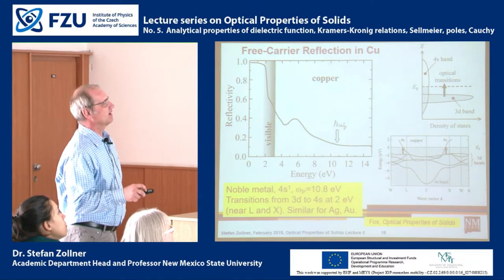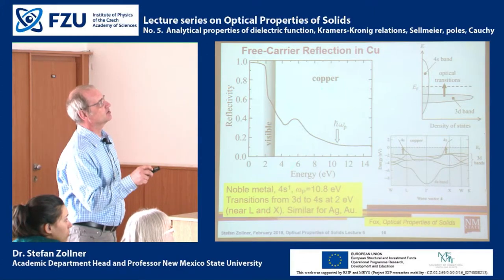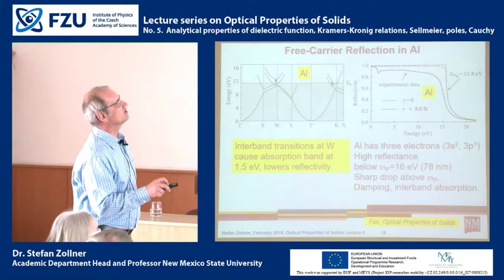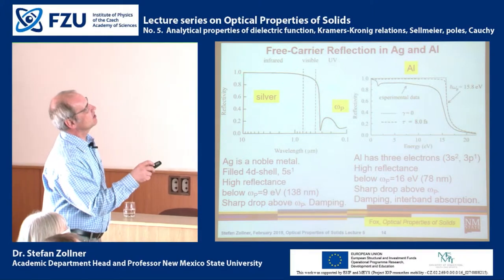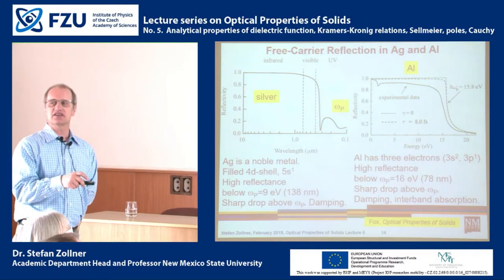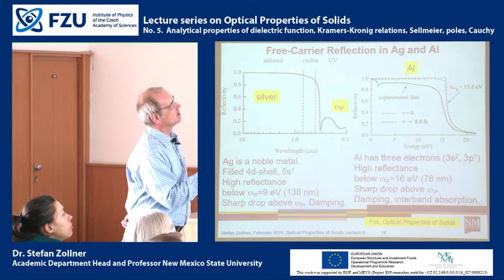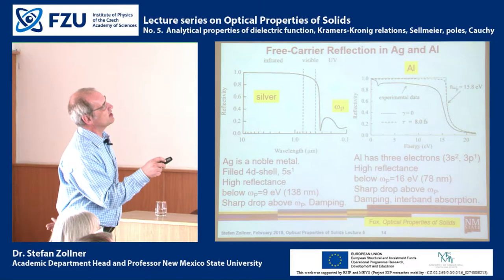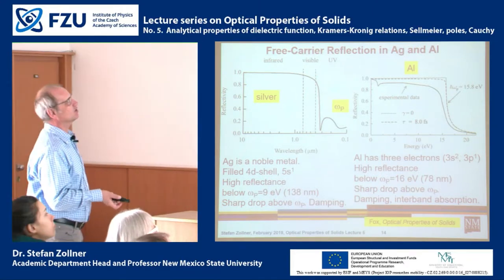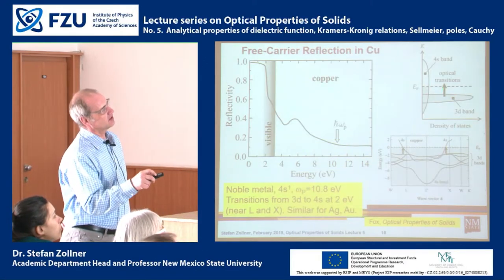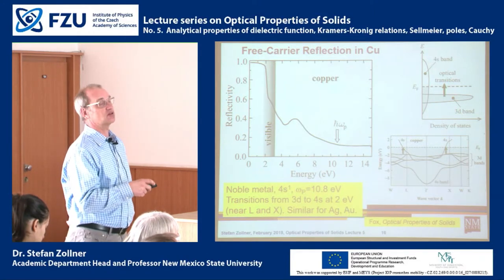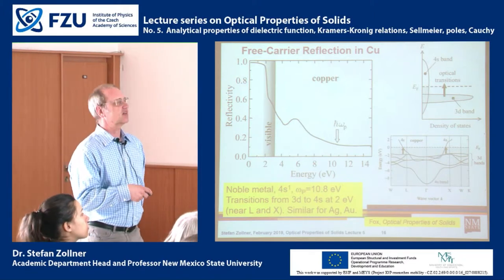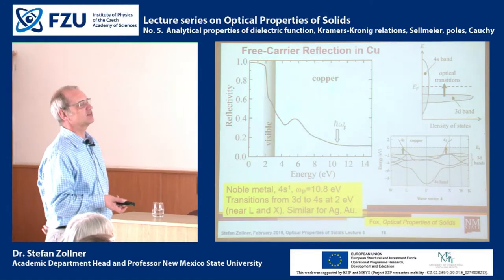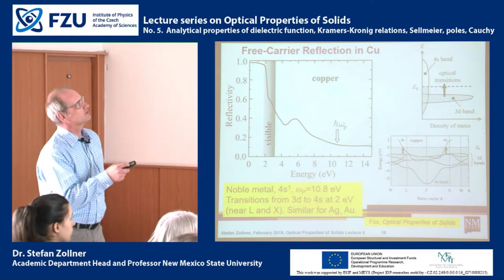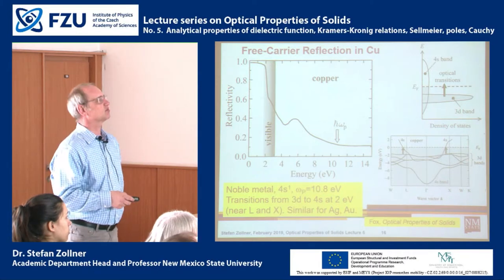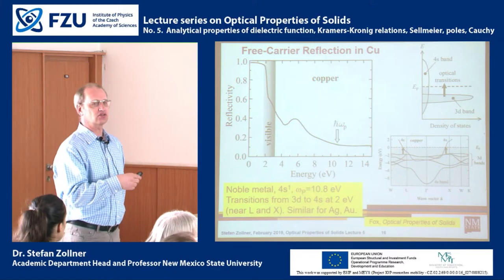So that's a noble metal. And silver and gold have similar properties to copper. However, the binding energy of the D band in silver is much larger than in copper or gold. And therefore, silver remains highly reflective at much higher photon energies than copper or gold. So this distance here varies between silver, copper, and gold. You're more likely to make visible mirrors with silver than with gold or copper. On the other hand, if you want to make really good infrared mirrors, then you would use gold, because then it doesn't matter that the reflectance drops in the visible. And that also explains the different colors of gold, silver, and copper.